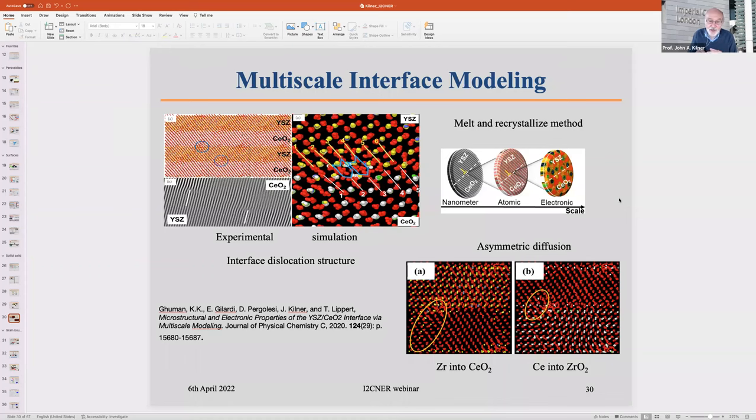As to the diffusivity, you've shown that water can affect diffusivity in some of these materials. I think there are a number of effects going on there. One is that you affect the non-stoichiometry of the material. You can introduce some extra oxygen vacancies as the effective PO2 goes down. And the other is, I think, that water will react with the grain boundaries. I can't prove this at the moment, but we do have some evidence that water penetrates down grain boundaries. I hope that answers your question. It was a bit of a complex answer.